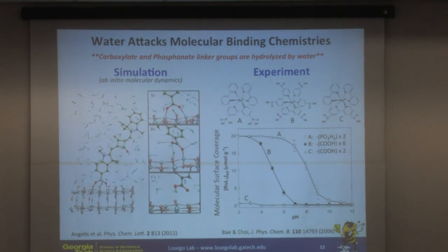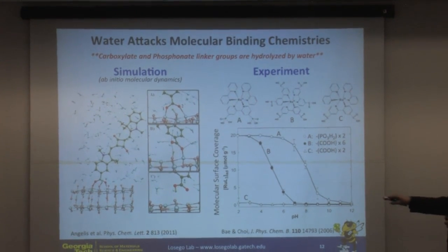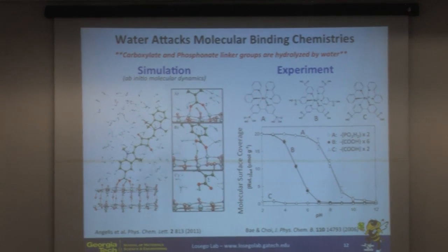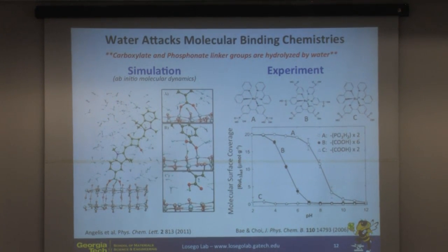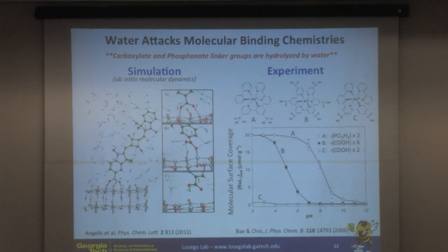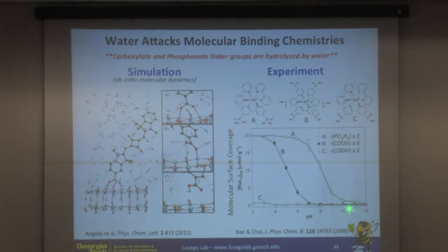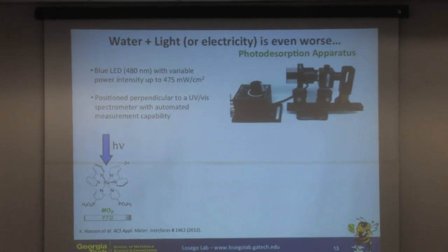So effectively, what we're seeing here is that as we go to higher pHs, this is what's done experimentally to analytically strip molecules from the surface. You go to higher pHs and you can completely remove any sort of dye molecule attached to an inorganic surface. Okay, so this problem even becomes more complicated when we add other stimuli, including light or electricity.